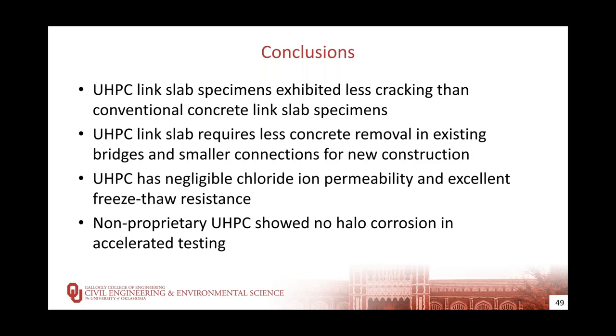UHPC has negligible chloride ion permeability and excellent freeze-thaw resistance, so it will behave very well in terms of long-term performance. And non-proprietary UHPC also shows no halo corrosion. Halo corrosion, again, as Clay had mentioned, is when you place fresh concrete against much older concrete, that difference in alkalinity content can actually cause existing steel in the existing sound concrete to start corroding. We did not see any of that in the non-proprietary UHPC accelerated testing.